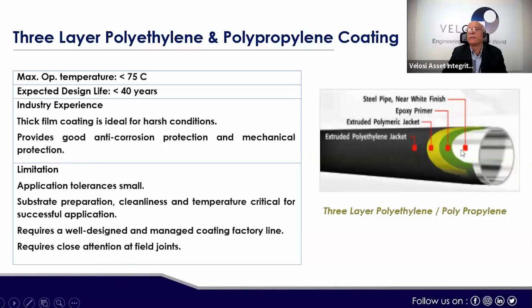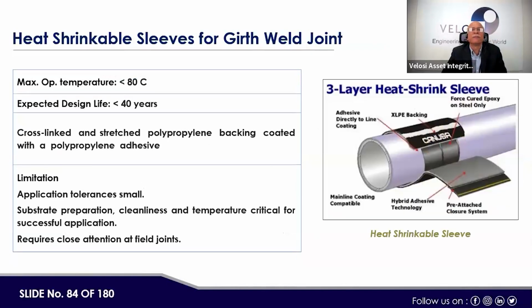Like here, three-layer: this is steel, then 1, 2, and 3. So these are the more common type of coating being used externally for pipelines nowadays. Then heat shrinkable sleeves for the girth weld joint. This is also important for the field joints. As you can see, there is the adhesive directly to line coating, then main line coating, then hybrid adhesive technology, a pre-attached closure system, and a fusion-cured epoxy on the steel.